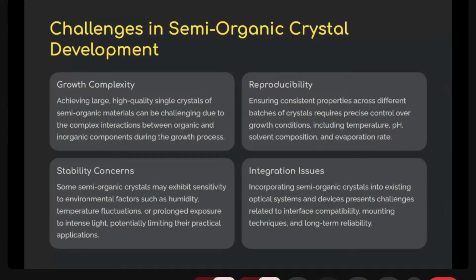What are the challenges in semi-organic crystals? Growth of high quality crystals, because we have to do multiple recrystallizations. For organic or inorganic crystals, we do not need multiple recrystallizations, but for semi-organic crystals, to get a transparent crystal, we need to do the recrystallization process three to four times. Then stability constraints: we need to see the temperature variation, because the melting point is about 180 to 194, which is very close.